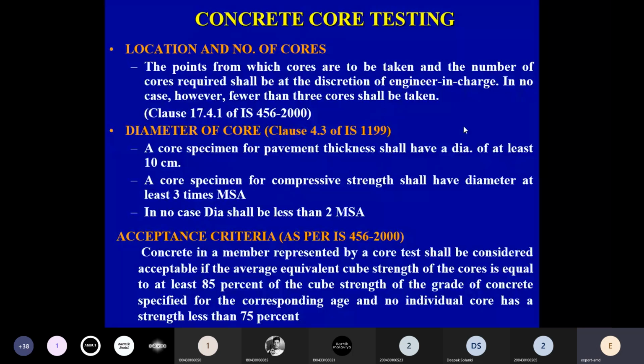Now in the latest code, we have also introduced the factor for diameter correction. It was earlier there in 1978 in SP 24, but since SP 24 was obsolete, it was not in use. So currently in the latest version, IS 516 2020, we have included the diameter correction factor also, where about 3 to 6% is a strength enhancement depending upon your diameter. You can refer to that code, IS 516, and you will get much of the information. But in no case shall the diameter be less than 2 times the maximum size of aggregate.